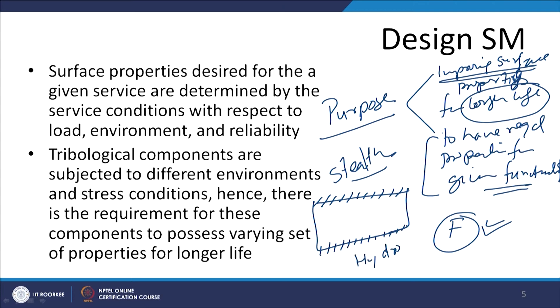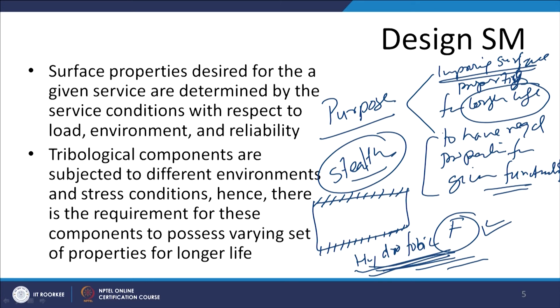For example, chemical vapour deposition and physical vapour deposition are processes which can modify a very thin layer in the range of 1 to 5 micrometres. Ion implantation can modify a depth of even less than 1 micrometre. On the other hand, weld surfacing methods can be used to modify surfaces up to a depth of 2 to 5 mm. So greater thicknesses can be achieved using one category of methods, while other methods can develop surfaces to a much smaller depth.